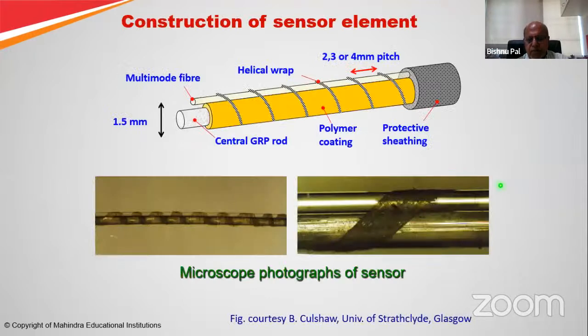Just one more sample of specialty fibers, for sensing. This is a multimode fiber, which is laid like this over a stretch of Kevlar, a material used in fiber cabling. This portion is the Kevlar region, and this yellow portion is a hydrogel material, which is a polymeric coating. Hydrogel is such that if it absorbs water, it swells. It is like the material in a baby's diaper. As water or urine gets in there, it swells up, so it grows.